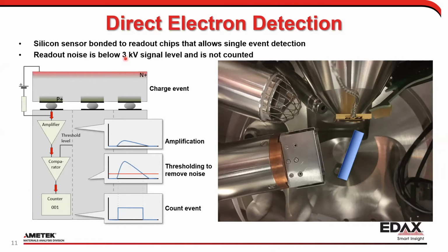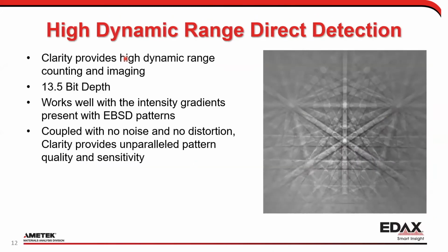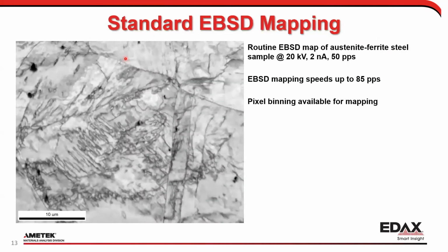In the end, when you do this, you get pretty patterns, right? This right here shows the high dynamic range of these patterns. They're 13.5 bit depth, and you can see very fine detail inside of these patterns because of that. This works very well because you have a relatively strong intensity gradient, so you can see that. Coupling this no noise and no distortion, you get unparalleled pattern quality with sensitivity that is almost crazy. Again, we've done work in the very, very low picoamp range.